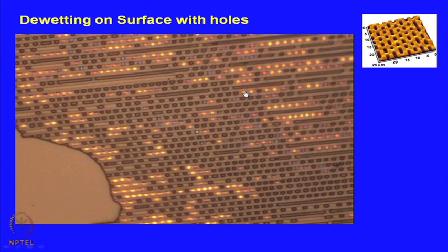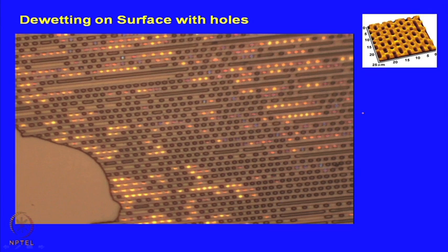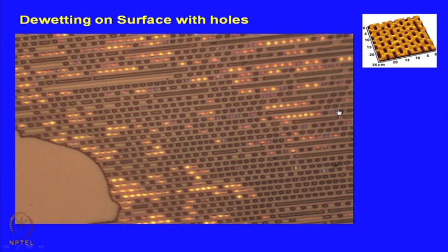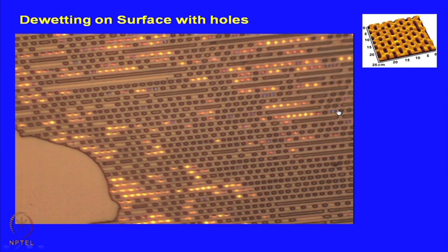Here you see some bright holes on which the film is still intact, which has not ruptured, and these brown colored holes are the zones over which the film has already ruptured. So, if I allow this video to run again, you see that some of these brighter holes are getting darker. What is happening is that the film is rather explosively rupturing over these zones. Okay. So, you can clearly see that the film is dewetting, it is rupturing over those zones, and finally,